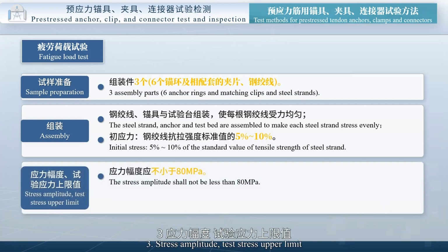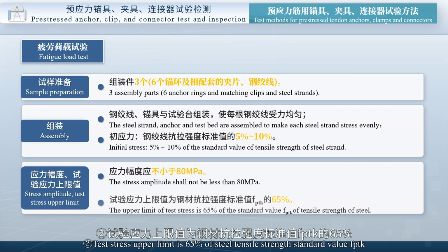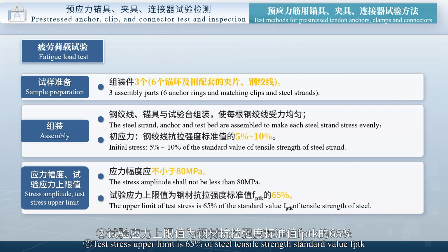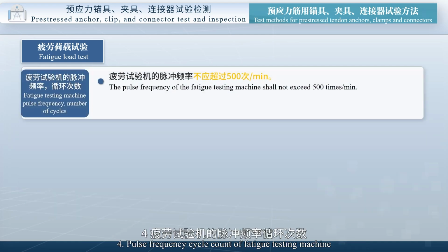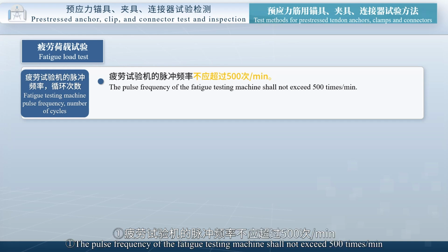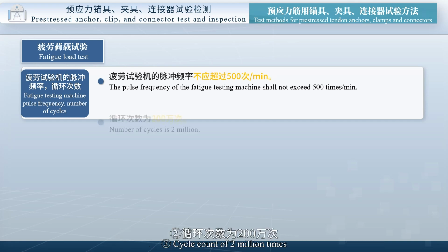Third, stress amplitude and test stress upper limit. First, the stress amplitude should not be less than 80 megapascals. Second, the test stress upper limit is 65% of the steel tensile strength standard value fptk. Fourth, pulse frequency and cycle count of the fatigue testing machine. First, the pulse frequency of the fatigue testing machine shall not exceed 500 times/min. Cycle count is 2 million times.